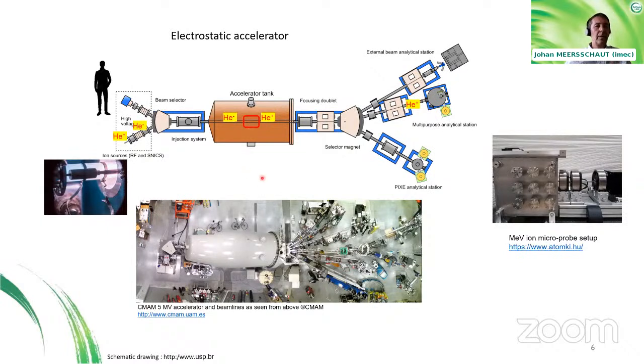And this is achieved by putting a high dielectric gas around this terminal so that you can avoid the discharges. And this is also why such an infrastructure has such a big size. So once you have accelerated the ions towards the terminal, a trick is used to convert the helium minus, so the anions, into positive ions, which are then further repelled from the positive terminal in the accelerator. And the energy of the exiting ion is double the energy of a single acceleration stage.